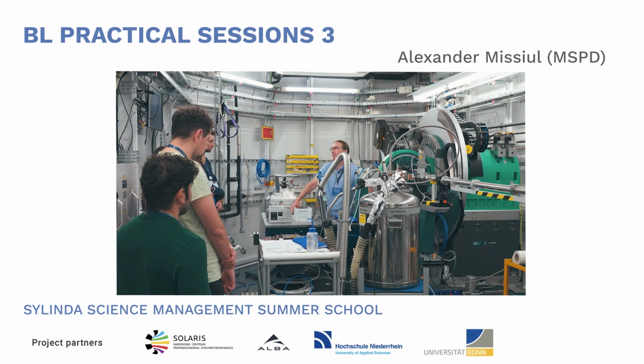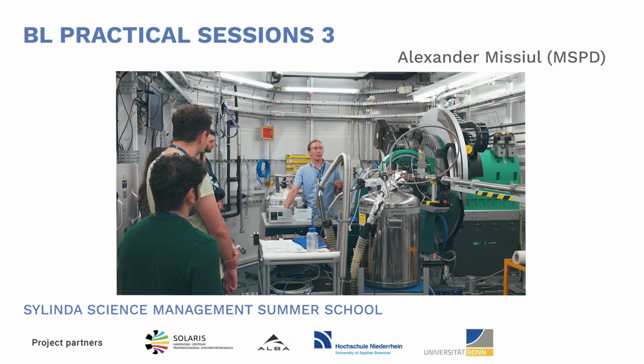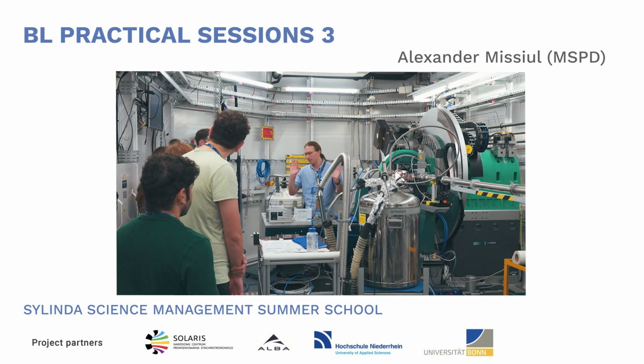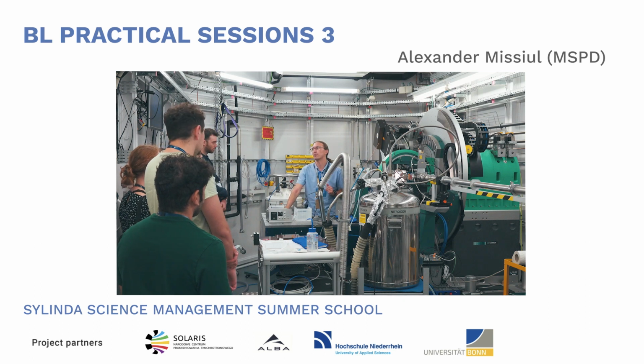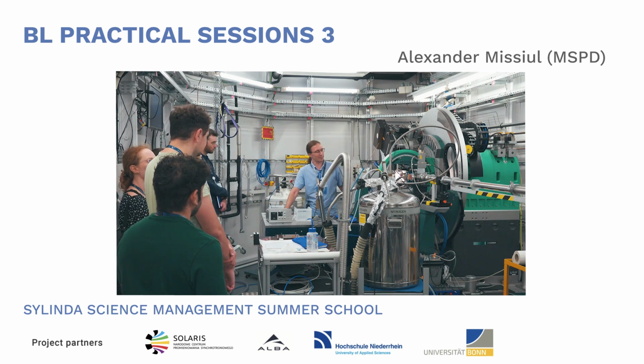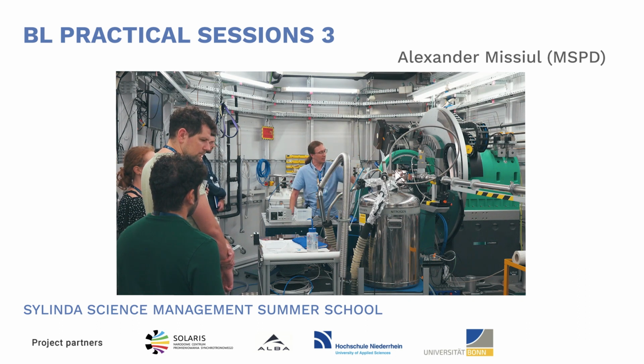The one at the bottom is a linear detector. Here we have a bit lower angular resolution, still much better than you might obtain with your laboratory diffractometer, but a bit less than here. The good thing is that experiments with this one are much faster. Normally we can follow the transformations inside the material in real time. The typical measurement time with the first one is approximately 1 hour, maybe 40 minutes. And with this one, we can collect a pattern good enough for refinement already in 1 minute, normally, or even faster. It depends on the quality of the material itself.